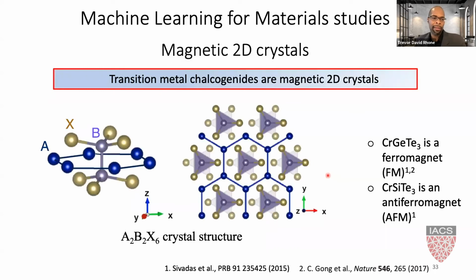So let's talk about these chromium germanium telluride compounds again. So chromium germanium telluride is ferromagnetic, and this is a crystal structure. It has this A2B2X6 crystal structure, where the chromium sites are sitting at the A sites, the germanium is at the B site, and the tellurium is at the X. 3 X is above the plane and below the plane. By the way, this plot just shows a unit cell, so some part of the crystal structure extends in X and Y direction. If you take a top-down view, again, it extends in X and Y.